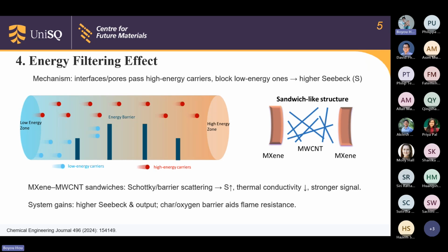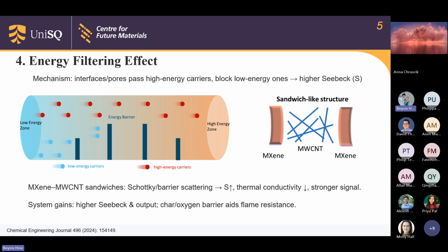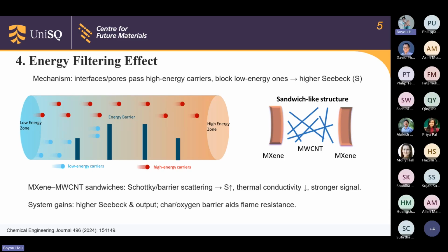Researchers built a sandwich-like structure, MXene sheets on both sides, and a web of multi-walled carbon nanotubes in the middle. The key is the height and the spacing of those barriers. If the barriers are too high or too dense, the current becomes too small. If they are too low or too sparse, the effect is weak. We tune this balance so that even a small early temperature difference creates a clear voltage signal. That signal is strong enough for a simple circuit to warn of the fire.